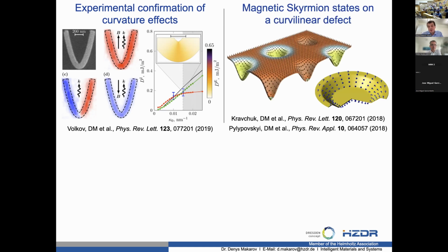You can use the same knowledge of the possibility to impose the Dzyaloshinskii-Moriya interaction to create skyrmions, this solitonic type of excitation, based on materials with extreme curvature radii, as shown here. This is also work of two Ukrainian scientists, Volodymyr Kravchuk and Oleksandr Pylypovskyi, where you can nicely see that there will be a possibility to create such solitonic objects in geometrically curved magnetic thin films.